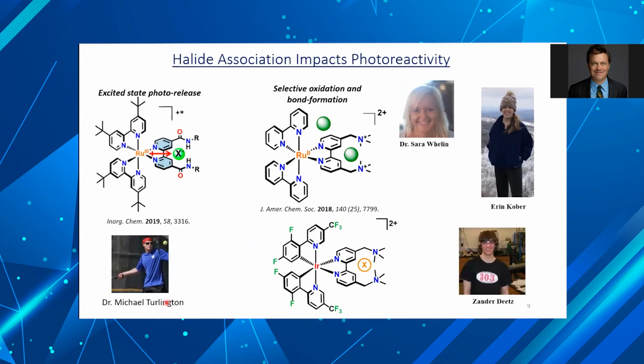We've learned a lot. Michael Turlington, who just graduated and is starting a postdoc with Kirk Schanze in Texas, found that if he had a halide just hydrogen bonded here, in some cases he could photorelease that halide. It wasn't exactly behavior we were looking for, but it was interesting to us, and he pursued that. Sarah and now Aaron were looking at cases that were more similar to Wes's, where we could get two halides very close to each other. And we're wondering, could it be possible to have electron transfer and I-I bond formation occur very rapidly, or perhaps even in one concerted step?